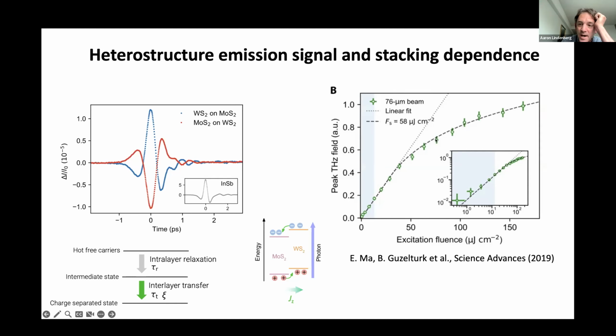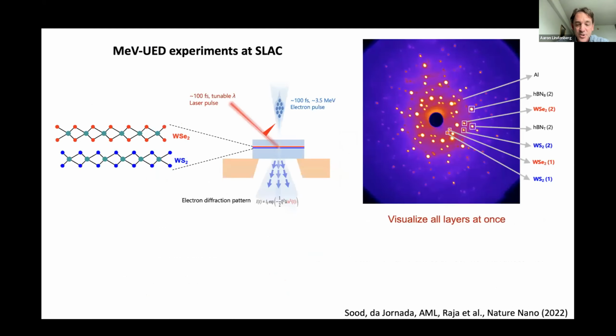And then we also saw, interestingly enough, the emergence of saturated behavior, which we can relate to the buildup of electric fields across the interfaces as this charge transfer process occurs. Okay, and there are ongoing measurements now, which I won't talk about, doing these measurements as a function of the twist angle of these heterostructures.